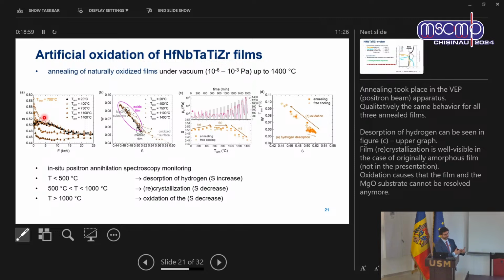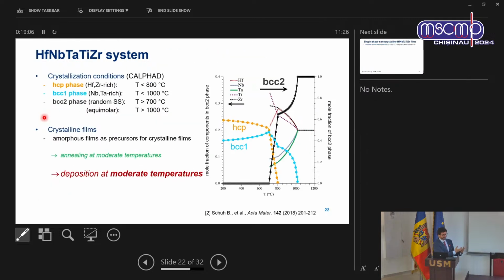So we needed to get back. We had limitations of our deposition system. We had limitations also of our samples and their composition, but we still wanted to produce the single high entropy phase. So then we got an idea that instead of trying to get to the temperature of 1000 and more, let's probe the intermediate region of moderate temperatures and see what will happen. Maybe utilize this amorphous structure as a precursor for this high entropy phase. And I have to say we were successful in this matter.